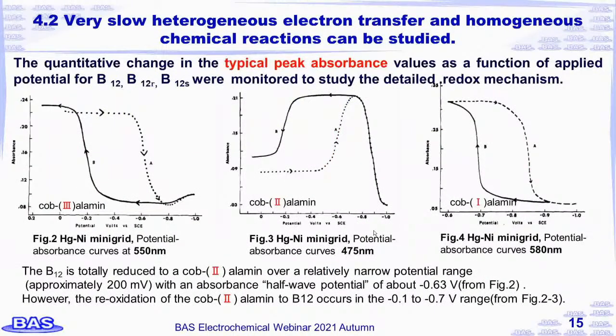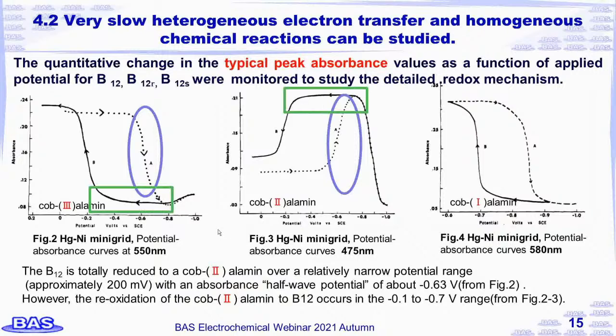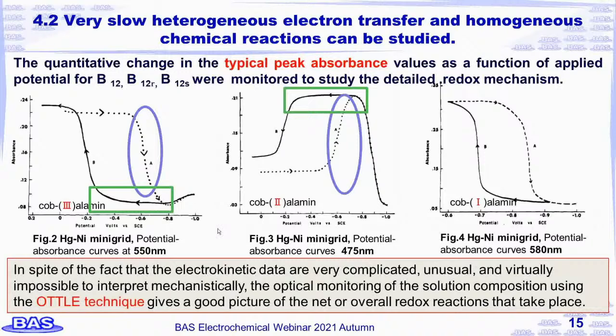The quantitative change in the typical peak absorbance values as a function of applied potential for vitamin B12 is monitored to study the detailed redox mechanism. From the potential absorbance curves at the respective peaks, it is known that B12 is totally reduced to a cob-(II)alamin over a relatively narrow potential range. However, reoxidation occurs in a broader range. This research showed that, in spite of the fact that the electrokinetic data are very complicated, unusual, and virtually impossible to interpret mechanistically, optical monitoring of the solution composition using the OTTLE technique gives a good picture of the net or overall redox reactions that take place.